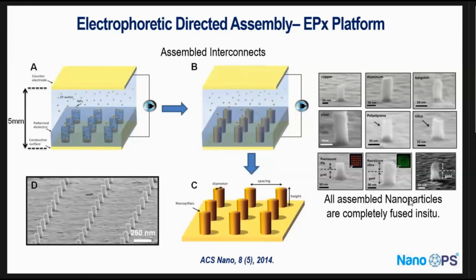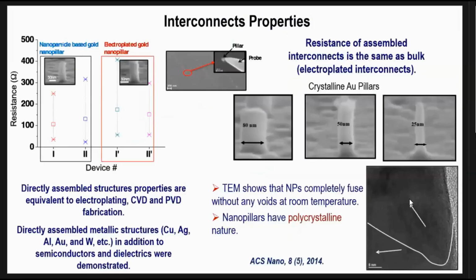You need a suspension of nanoscale particles. In this case, it's gold particles. But you can see that we've used copper, aluminum, tungsten, and a variety of other materials. You can also use dielectric or semiconductor. And typically an aqueous solution is the best, but you can also use other suspensions.